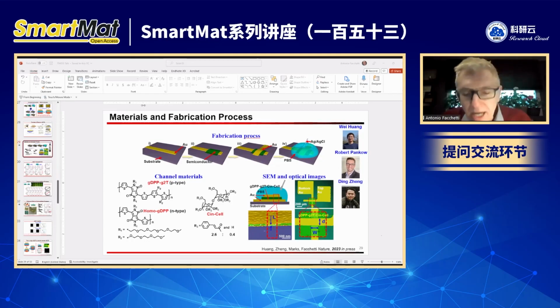Usually, this is well known to a certain extent in the sense that many of the conjugated polymers which are the most performing are very textured, right? Very crystalline. And crystallinity usually is associated with a higher modulus. So one way to work around that is to have either a semi-crystalline or close to amorphous polymer, and at the same time have good charge transport. These two properties usually contradict each other. The best strategy, and this has been shown by the work of others, is to create fibers of a very textured area blended with an amorphous region of the same polymer, and this is where you usually get the best results.